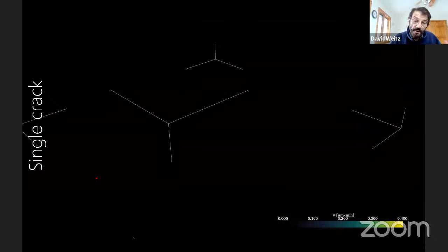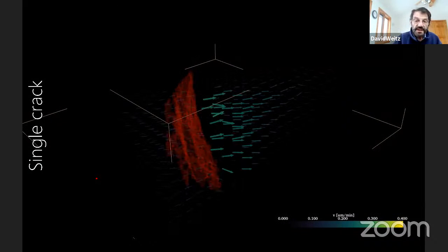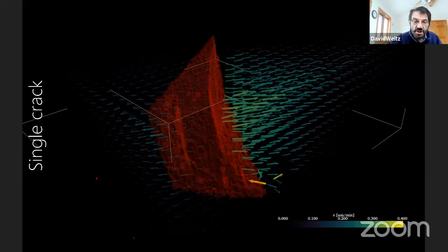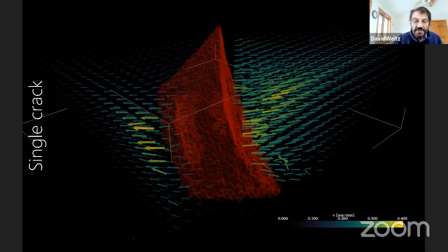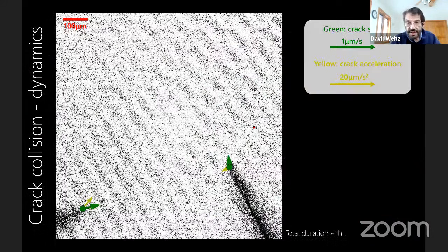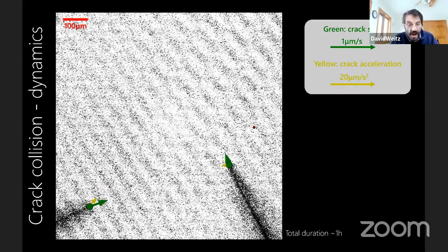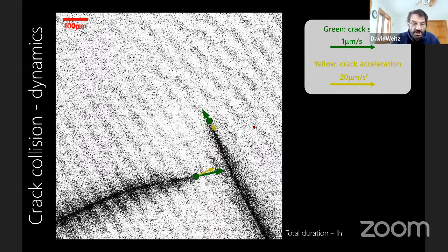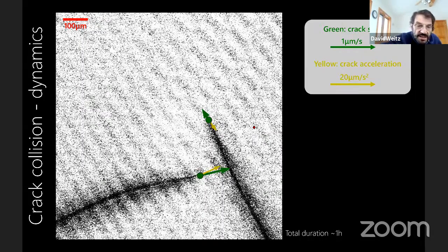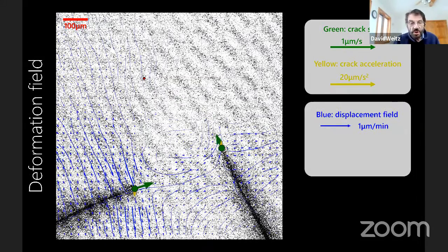First of all, because it's a confocal image, you can actually see the three-dimensional image of the crack, and these are just showing the crack itself, and the arrows show the motion of the strain field around the sample. So let's go back and look at the behavior. I showed you this ability to image the crack and measure the velocity, but now you can measure the whole strain field. You just look at the speckles over there, and you can measure the whole strain field. And these blue arrows show the strain field.